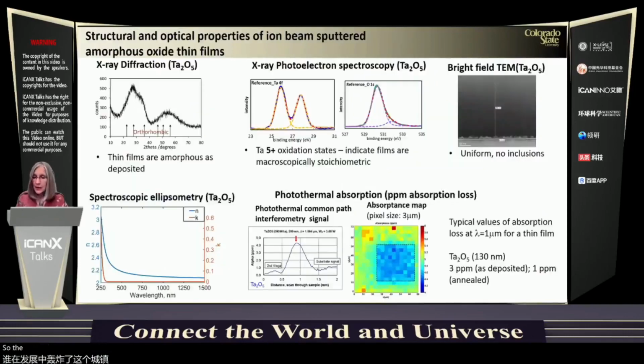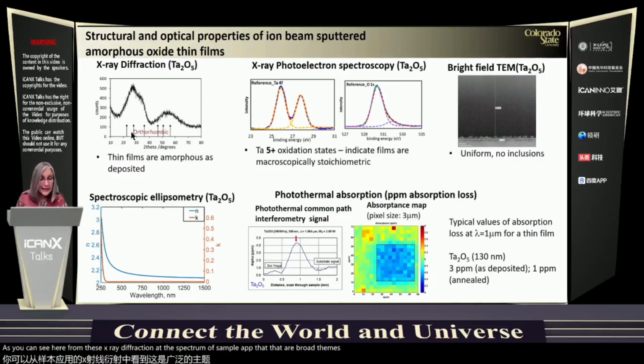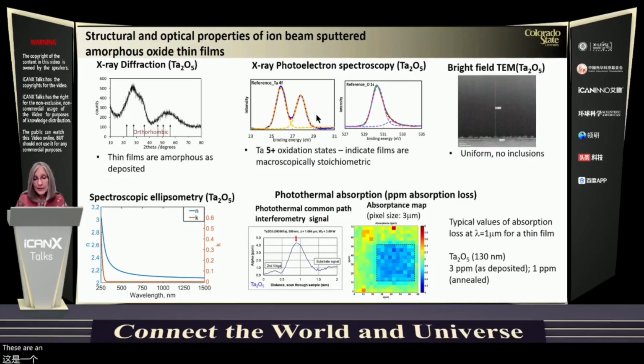So the materials that are synthesized are amorphous. As you can see here from this X-ray diffraction spectrum of tantala, there are broad peaks. These arrows indicate where the peaks of the crystalline orthorhombic tantala should be. Macroscopically, they are also stoichiometric, as shown by these X-ray photoelectron spectra, and they are very uniform, as shown by this transmission electron microscope image.